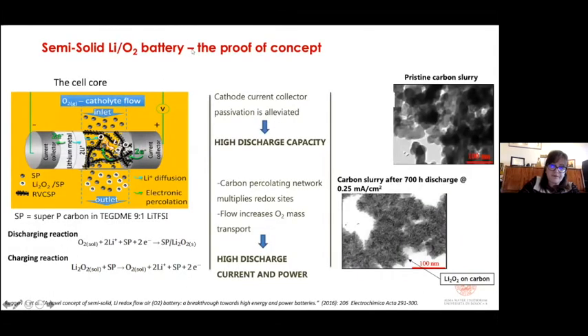Well, a few years ago, we developed a new concept of lithium oxygen battery. We call it a semi-solid flow lithium oxygen battery. In our system, we have a lithium metal, a separator with electrolyte, and a porous current collector, but the porous current collector intercepts a semi-solid fluid, a fluid that is composed of the oxygen-enriched electrolyte where carbon particles are dispersed. So this fluid is electronically conductive. Well, in this cell, oxygen reduction takes place on the carbon particles that intercept the current collectors. It means that the cathode current collector passivation is alleviated because the particles flow away.